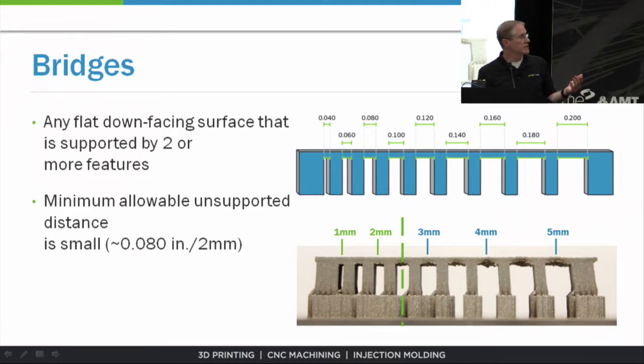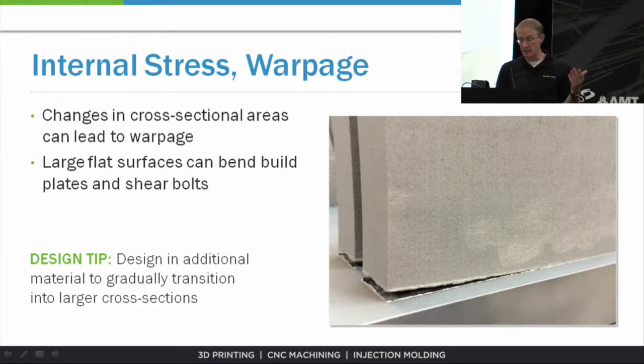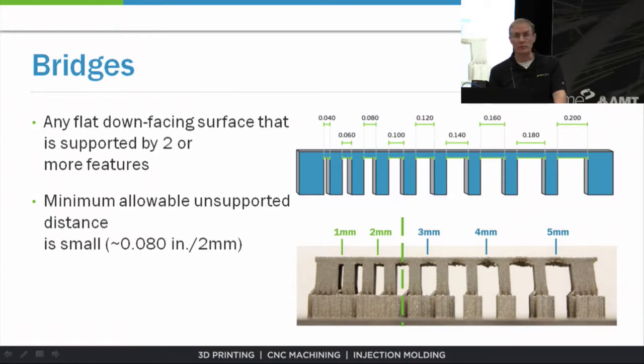Now, this is actually a really unique geometry as well, because it talks about another element of stress within this process, and that's large cross-sectional areas. You can see that when the bottom edge of the bridge surface came into the part, it pulled all of those legs inward, right? So this was actually designed to have vertical faces. But when that cross-sectional change came in, it literally pulled in all those legs. Now, in this case, we could solve that by flipping the geometry over and printing progressively smaller cross-sectional changes. But that's not always possible, right? Sometimes, because of the orientation of the part, you've got multiple areas that have wide cross-sectional changes. The other thing that we could do here is, instead of building vertical bridges, you could build in arches, right, that have a more gradual change.